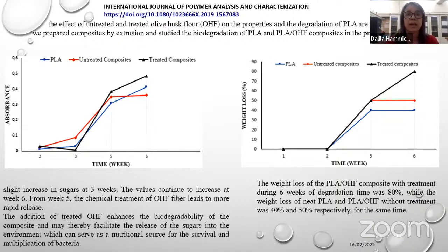So the addition of treated fiber enhances the biodegradability of the composite and may thereby facilitate the release of sugar into the environment, which can serve as a nutritional source for the bacteria, especially with treated fiber. We also saw that the weight loss of the composites with treatment during 6 weeks of degradation time was 80%, while the weight loss of neat PLA and the composite without treatment was 40 and 50% respectively. Here we can say that after treatment we have more degradation of this composite. So the treatment accelerates the degradation process of the composite.